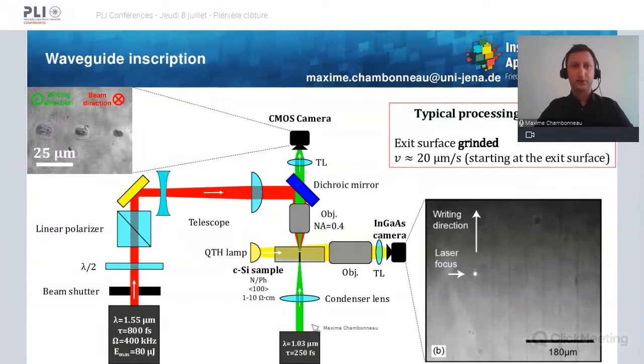Well, to answer all those questions, we have developed the following setup depicted here. It works at 1.55 micron wavelength with 800 femtosecond pulses. Then we adjust the input pulse energy as well as the beam size optically before the beam is focused to the silicon target by an objective lens. Besides, we have two microscopes working both in transmission, which allow us to basically monitor the interaction in a three-dimensional way. So what is the trick we have found for modifying bulk silicon?